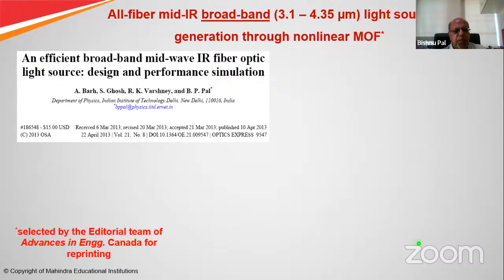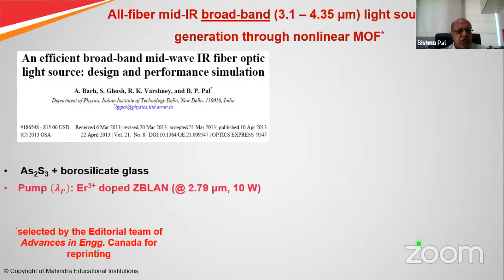We also did a broadband wavelength source from such a chalcogenide designed fiber with different design parameters, so that it emits wavelengths from 3.1 to 4.35 micrometer when it is pumped with a source which is an erbium doped ZBLAN laser.